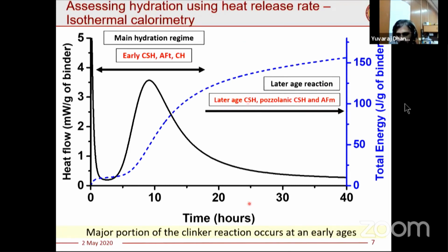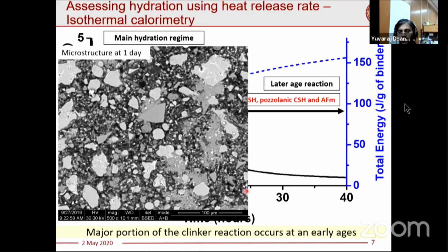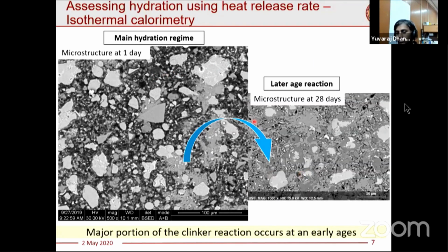So when you try to break open at 1 day and put a piece of cement on a microscope, this is how it looks. So these bright phases are unreacted cement. You can see that it started forming a lot of hydration products in between. And over the period of time, by 28 days, the microstructure of the cement becomes much more compact than what it is at 1 day. However, we need to understand that a major portion of the clinker reaction happens in the early ages.